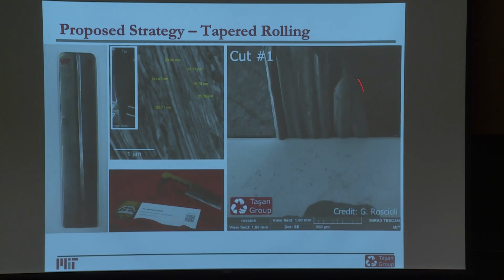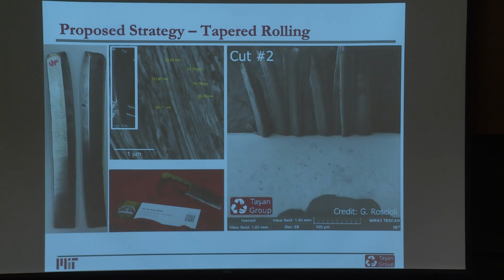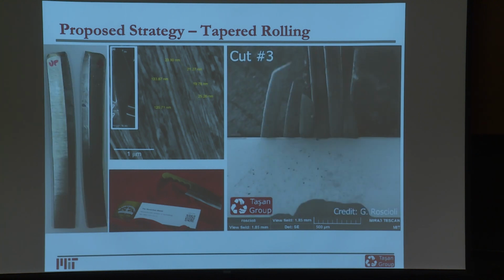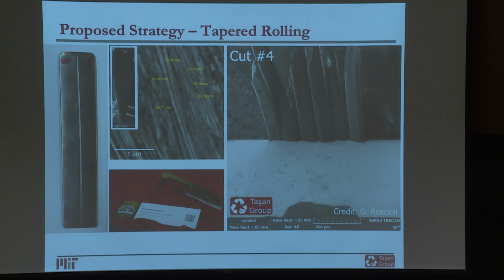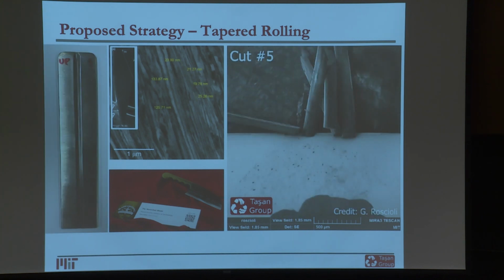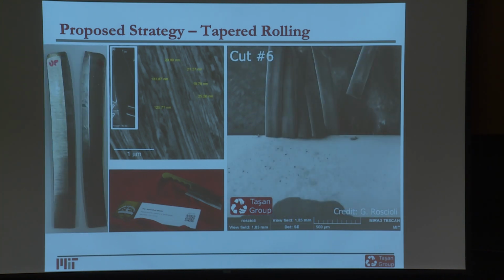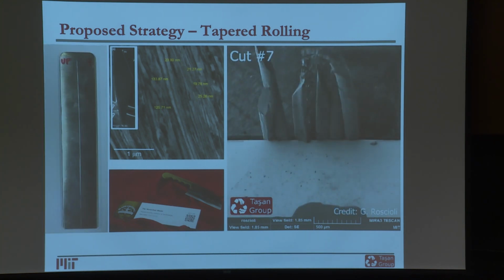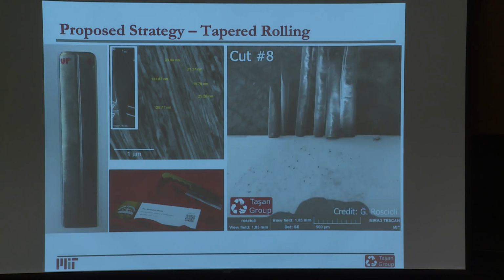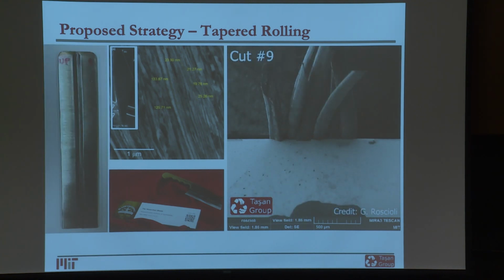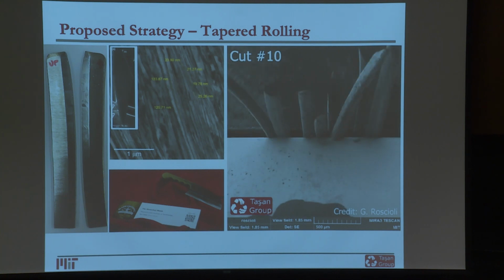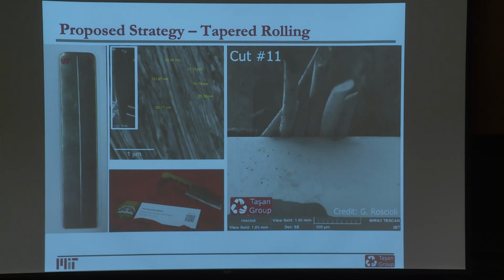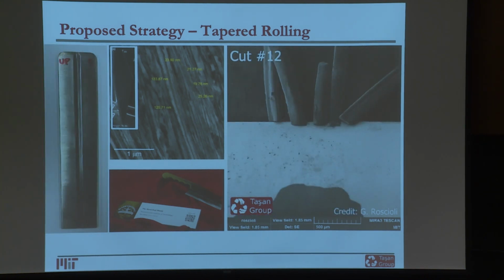And he repeated some of these experiments that he carried out with conventional blades and demonstrated that when you have this kind of idea where you produce a lot of deformation, so you create more homogeneous hardness and higher hardness, then you can actually cut hair tens of times. And this movie goes on, I think, to 24 or something, and you don't see any chip formation here.